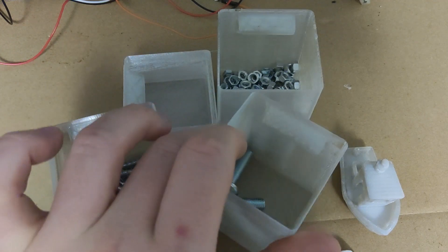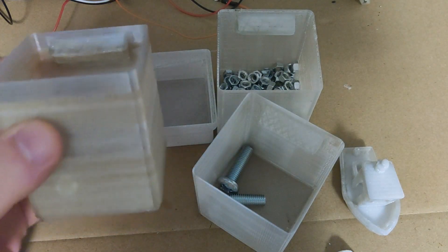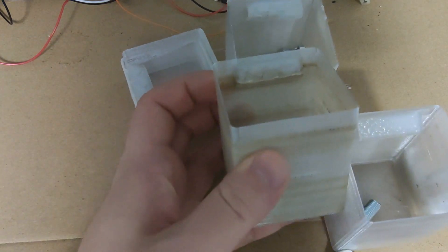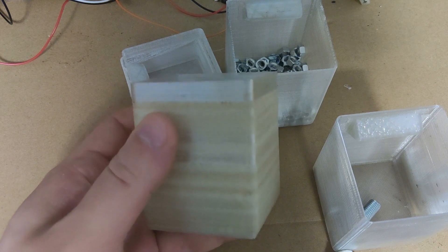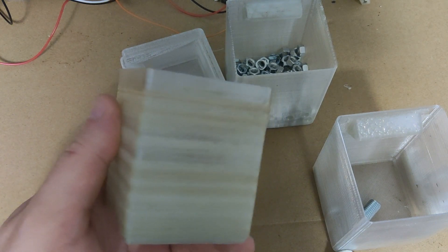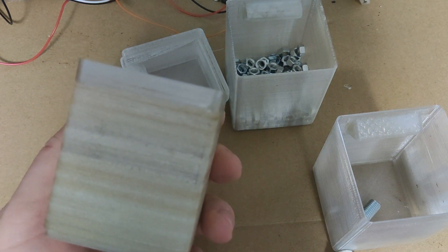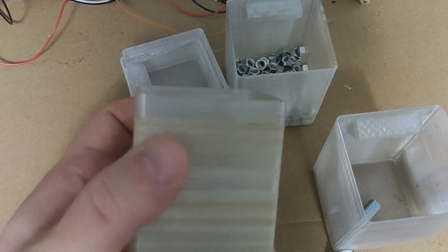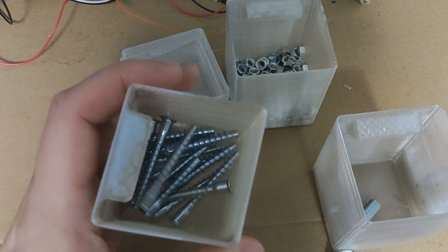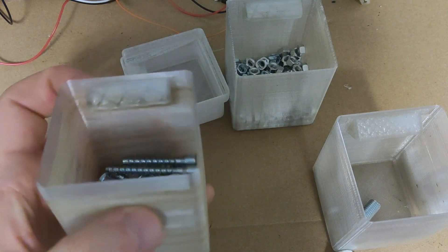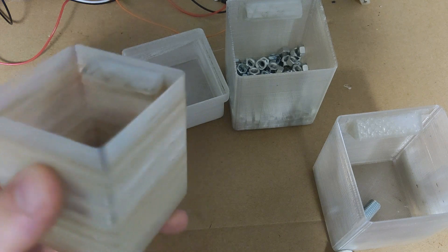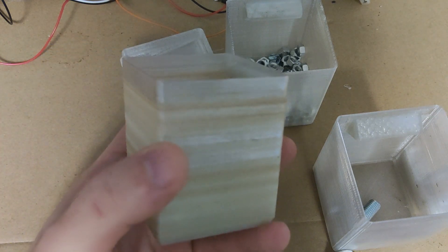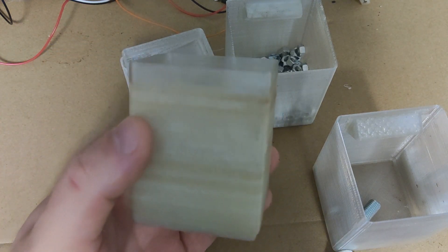Example number one is a box made from not cleaned cola bottle. As you can see it has brown lines all over the place which is most likely liquid trapped inside the hollow filament. At the very least I suggest using clean water to get rid of any residue fluid unless of course it was a water bottle.